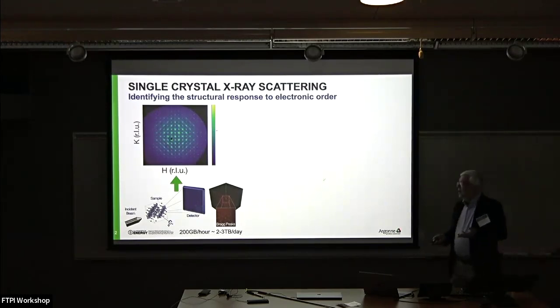And one thing I didn't mention is that because it's so short, of the order of half an hour to do a single measurement, sometimes even shorter now, you can measure lots of temperatures. For instance, in the morning, you can do 10, 20, 30 temperatures, allowing you to measure all the structural correlations over the entire phase diagram of a set of materials in just a few days.